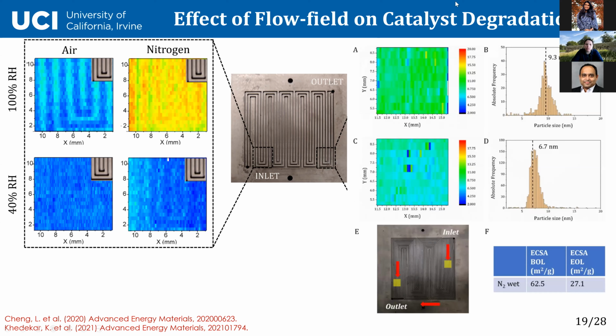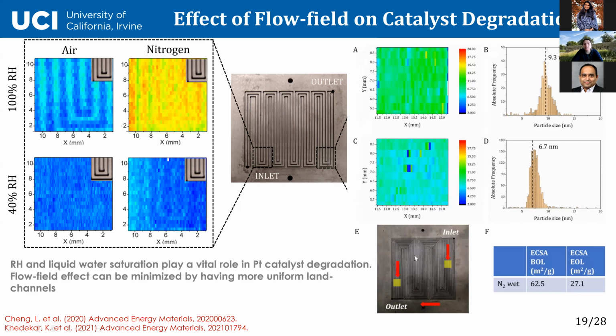And then when we looked at platinum size distribution, we no longer see differences between lands and channels. And that teaches us a lesson that when you have wide lands, here 1 millimeter, and channels, you have really inhomogeneous water distribution, and that drives degradation. So when you have narrower lands and channels, that prevents platinum from agglomeration.